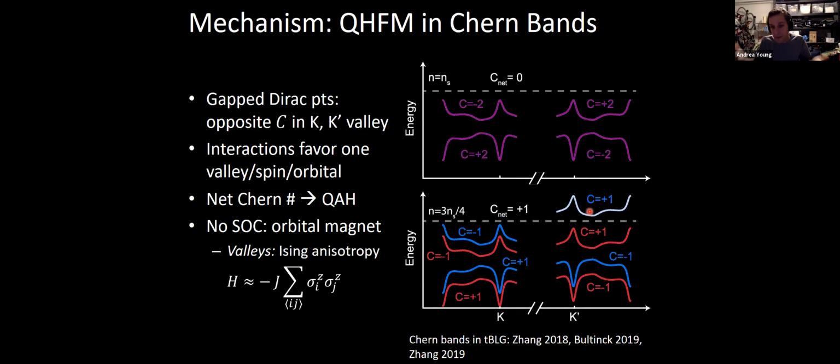And apparently from experiment, one would say this must be what's going on, because we see a quantized anomalous Hall effect, which you would not see, for example, if you had some ground state that was a superposition of states in the two different valleys. Interesting features of these magnets, besides that they have a finite Chern number, after all, quantum anomalous Hall effects have been observed, although in very different systems, as I'll discuss, is that most of the time one gets ferromagnetism from strong interactions, fine, and spin-orbit coupling, which is what gives you anisotropy.